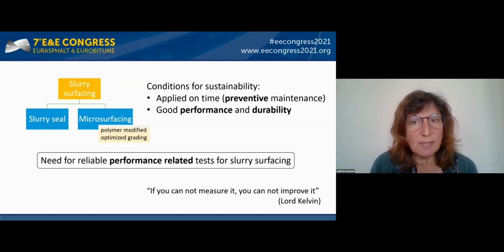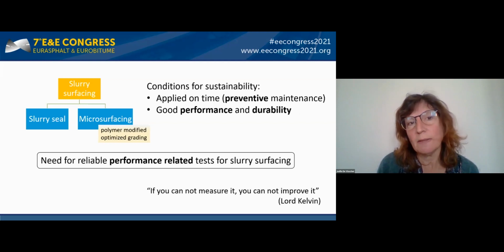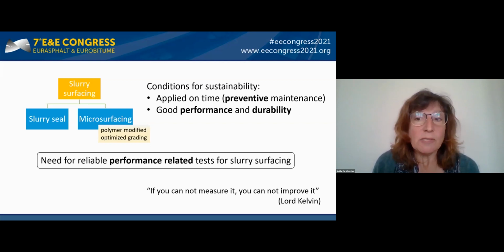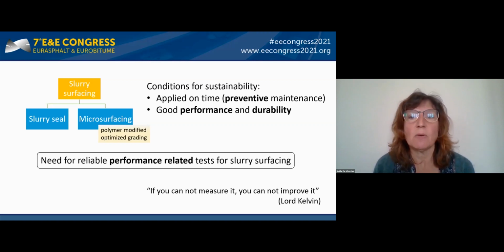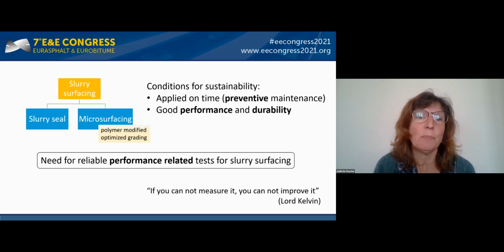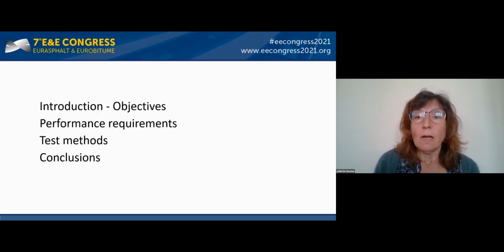So when we speak of slurry surfacing, we mean both slurry seals and microsurfacing, two technologies which are not fundamentally different, except that microsurfacings provide more strength and stability because of the polymer modified emulsion and the optimized grading. Slurry surfacing is very sustainable, provided that it is applied on time and that the slurry mixtures are durable and will perform well for many years. And a key to good performance are reliable test methods, because as we all know, if you cannot measure it, you cannot improve it. After a brief introduction, we will sum up the main performance requirements of slurries and then discuss the related test methods to end with the conclusions.